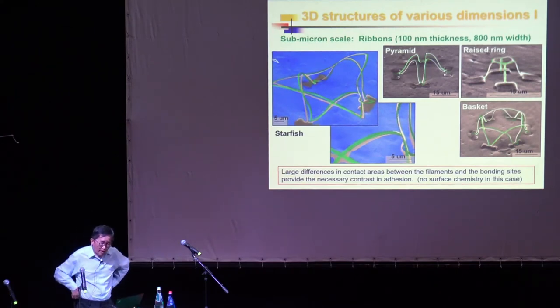So how do we overcome that challenge to pop up structures smaller than 30 nanometers? It's doable, but it's more costly. The way to do it is you have a structure, let's say very thin, 1 nanometer. What you do is you sandwich this 1 nanometer structure: on top and bottom, you put other materials, but thicker. So altogether, it can be 30 nanometers, 40 nanometers. 30 and 40 nanometers is not a problem, you can pop them up. But after you pop them up, you chemically dissolve the top and bottom sandwich layers to leave the middle layer, to save the middle layer, okay?